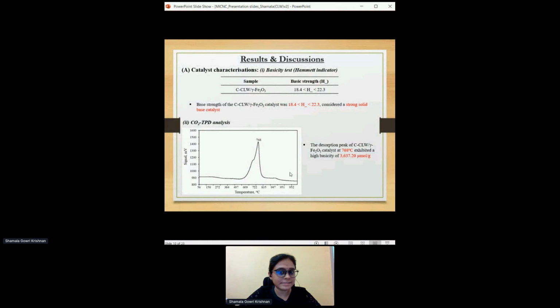In the first stage of results and discussion, we began with the basicity tests on the solid base catalyst we produced, and we found that this catalyst actually generates a very strong base. With the help of the Hammett indicator, we detected that the catalyst has a strong basicity in the range from 18.4 to 22.3, which is considered a strong base. These results are in line with our CO2-TPD analysis, which shows the catalyst has a very high basicity of 3637.2 micromole per gram. In the temperature range between 600 and 800, it actually generates very strong basic sites.